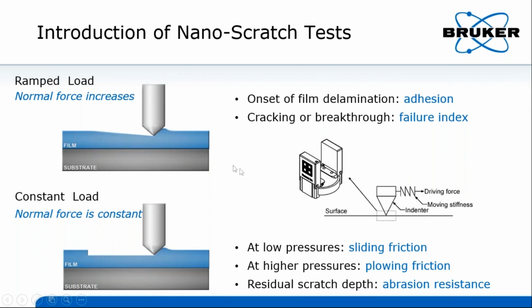On the other hand, we also applied nanoscratch to measure the nitride-copper adhesion. The nanoscratch test is quite flexible and can be set up in a number of ways, but there are two main categories of tests usually employed. In a scratch test, the lateral axis is always operated in displacement control feedback, so the user specifies a scratch length and the speed. In the normal axis, it can be operated in either load or displacement control, but load control is more common.